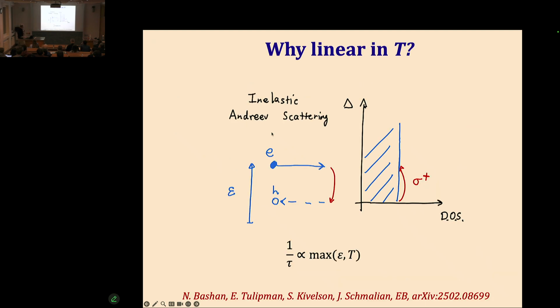And finally, let me just end with this. I won't go into the details of the analysis of this model. Let me just say, why do you get linear in T from this problem? There's actually a very simple argument. We have this parameter delta that controls the offset between the two lowest energy levels of our superconducting island. So suppose this parameter delta just has a uniform distribution. In most of the puddles, we have a finite energy splitting between the ground state and the first excited state with n+1 Cooper pairs.